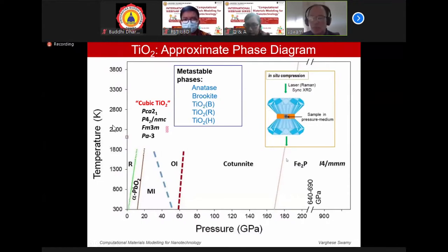I mentioned earlier, I was interested in high pressure or the mechanical behavior of these materials. How is the experiment carried out? For the experimental study of materials under high pressure and temperature, we use what's called a diamond anvil cell. That's what is shown here symbolically. These are two diamond crystals, and on the top of one face and bottom of the other face, we put a metal gasket and drill a small hole, 300 micrometers or whatever.